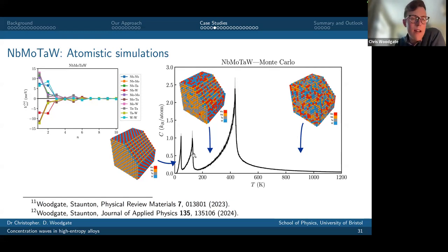And then at really low temperatures, which are not really experimentally accessible, but are kind of interesting as a theorist, the model suggests that there are these two additional last little coughs in the heat capacity. And what they're actually describing is eventual sublattice orderings on both of the simple cubic sublattices. And you end up with the model suggesting that there is a single phase ground state structure for this system, which is this kind of Heusler-like structure that I'm illustrating just here. And I should say this top left panel.